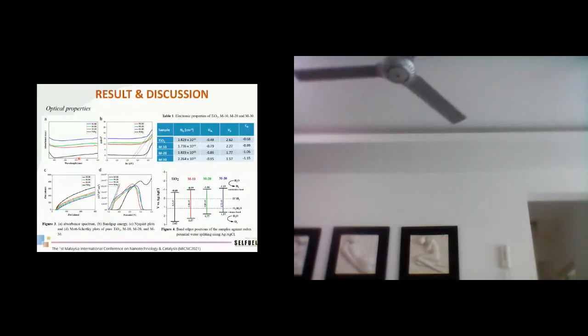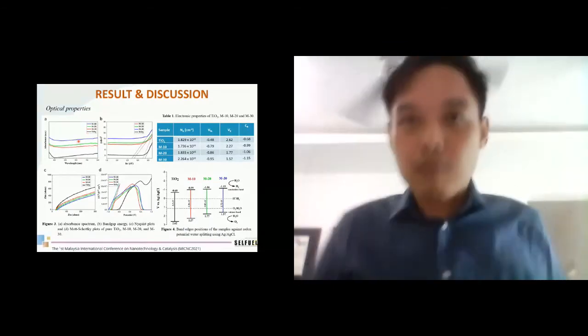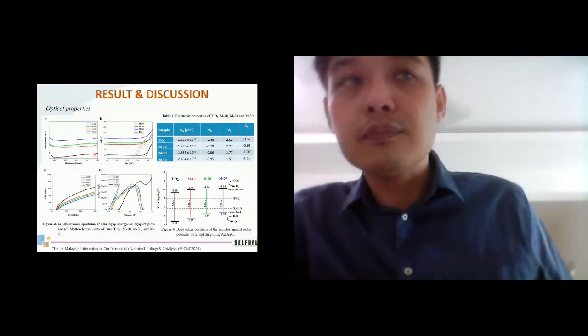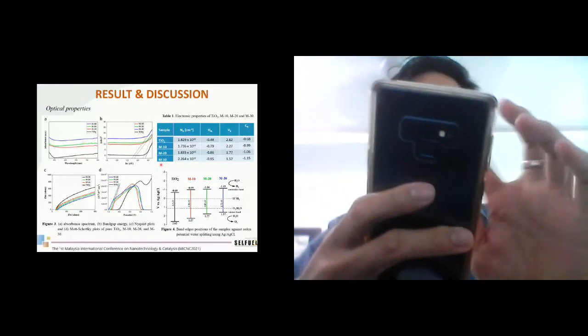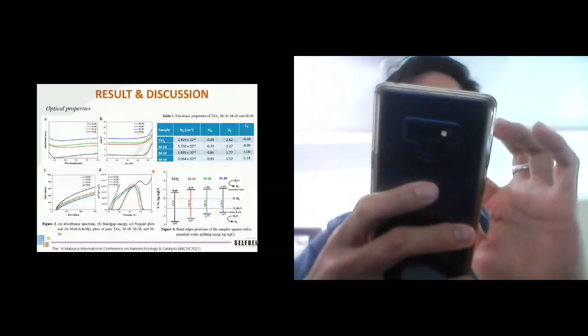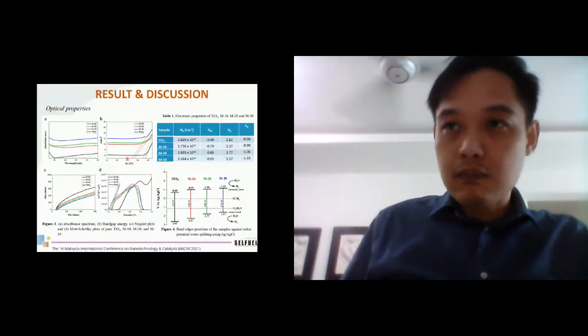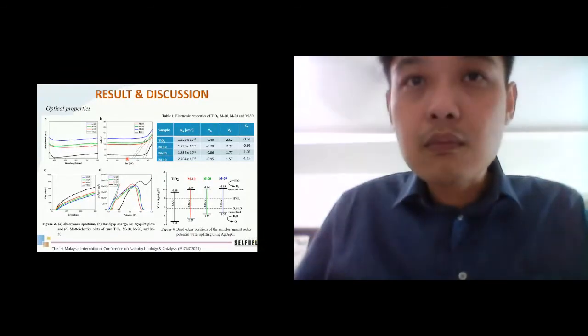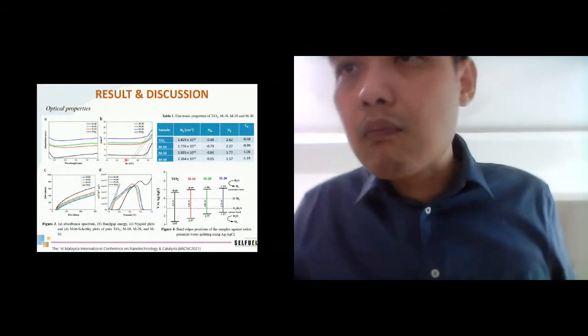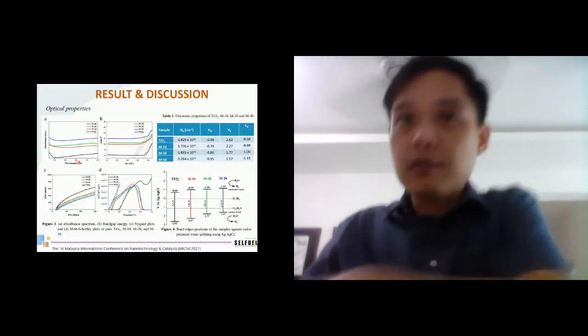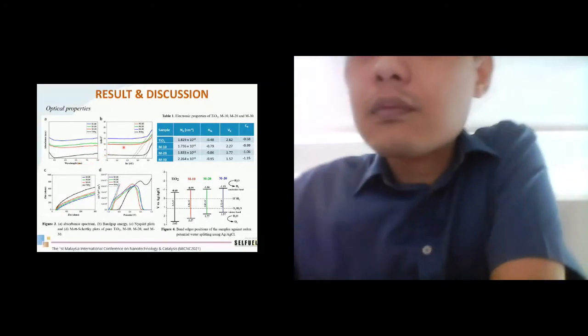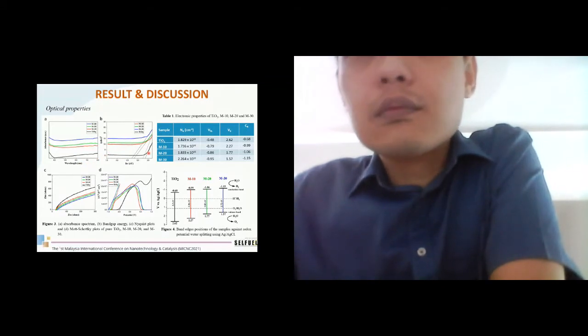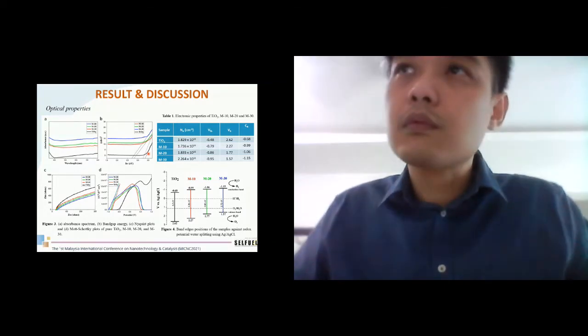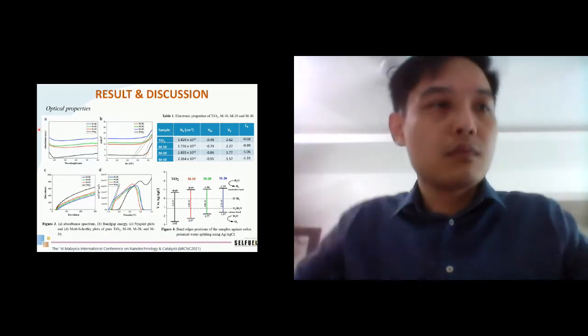Okay, these are the optical properties of the samples. Figures A and B show the absorption and band gap determination of the samples. The pure TiO2 absorbs the lowest light energy compared to all composite samples, and the band gap value is about 3.3 electron volt. Meanwhile, the band gap of M10 is slightly lower, about 3.26 electron volt, while the band gaps of M20 and M30 are 2.83 and 2.72 electron volt respectively. The reduction of band gap energy is due to the increased sensitivity of the TiO2 to visible light with the presence of CoS. As we know, CoS is able to capture visible light energy better than TiO2 because it has a smaller band gap.